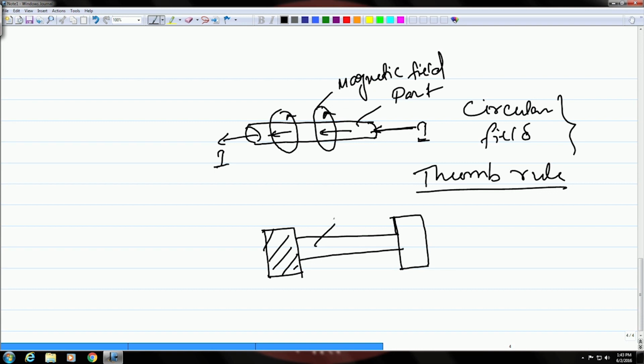Okay, so this is the part or the sample to be examined, and you connect it between two electrodes at either end. One of them could be movable, so that you can move it and push it against the part and make tight contact, and another on the other side will be fixed.